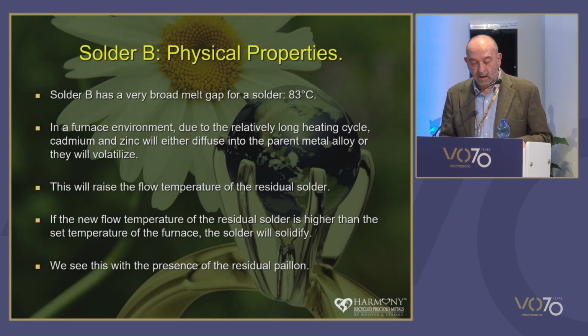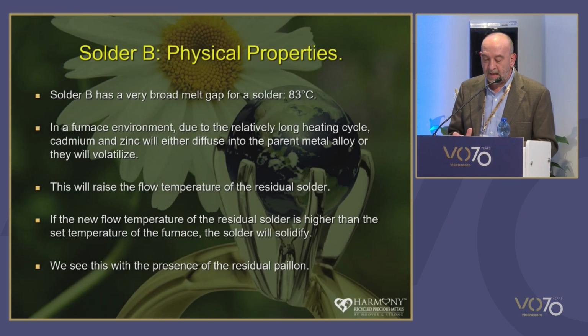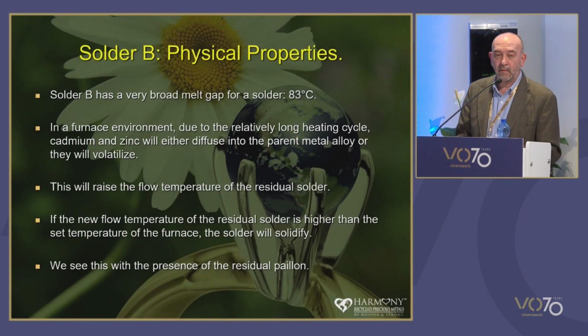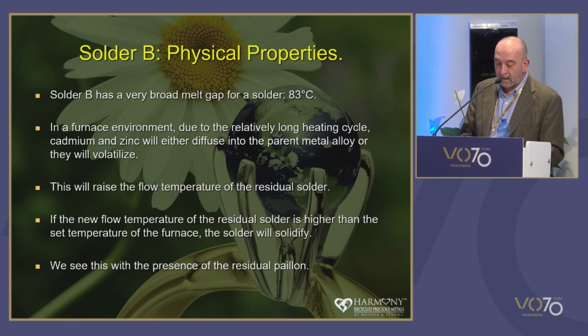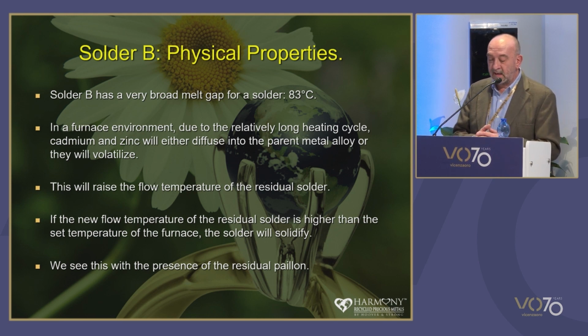Other properties we can look at. Solder B has a very broad melt gap at 83 degrees centigrade. In a furnace environment, it's going to take a significant amount of time, relatively, to raise the temperature of this solder from melt to flow point.